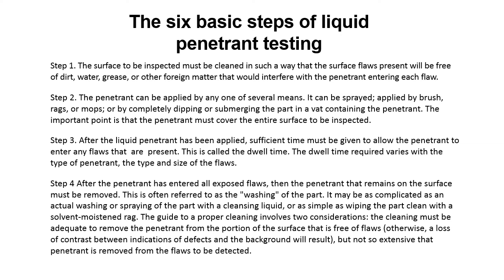The guide to proper cleaning involves two considerations. The cleaning must be adequate to remove the penetrant from the portion of the surface that is free of flaws — otherwise a loss of contrast between the indications of defects and the background will result — but not so extensive that the penetrant is removed from the flaws to be detected.